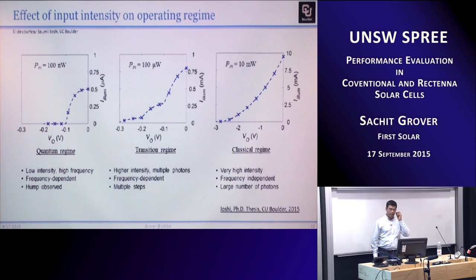So here's a comparison of IV curves for the three different regimes that I've shown in the previous slide. Low intensity, high frequency, and the frequency here, if you look at this IV curve, is essentially given by a tenth of an eV, because that's the maximum voltage that is developed by this solar cell. Now, this is higher intensity, and with that, we have multiple photon processes happening. So with the higher intensity, you can see that not only do we have a tenth of an eV photon step, but also a 2/10 of an eV photon step, and a 3/10.